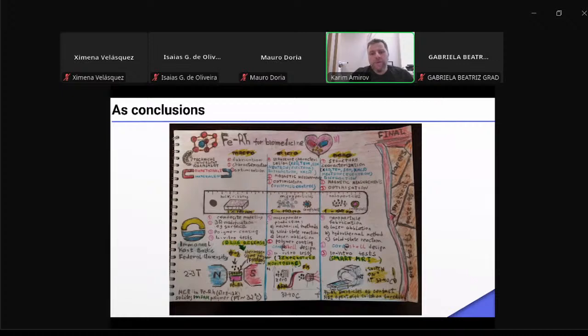In conclusion, iron rhodium demonstrates good opportunities for application in biomedicine. Maybe other alloys from the noble metal group can also be used. But our preliminary experiments with gadolinium showed that this material is toxic. It cannot be used in biomedicine. So finally, the point is that the magnetocaloric effect can be used in biomedicine. Firstly, we use the heat.